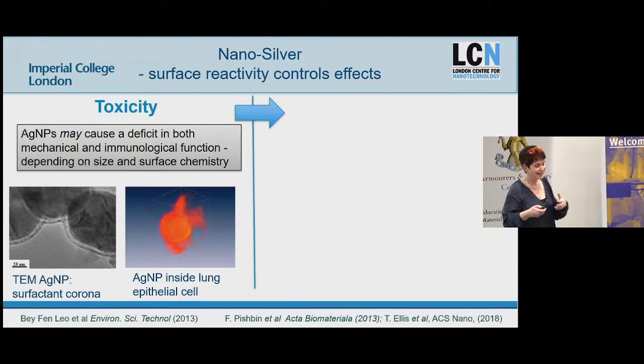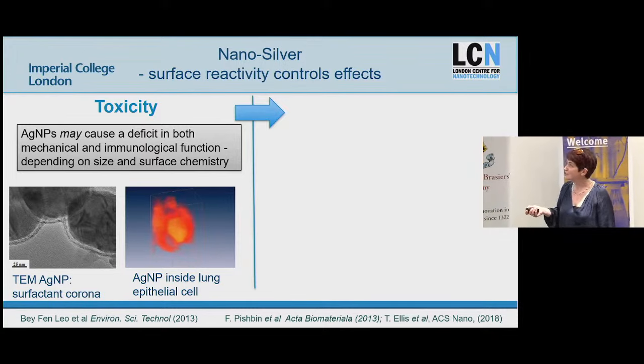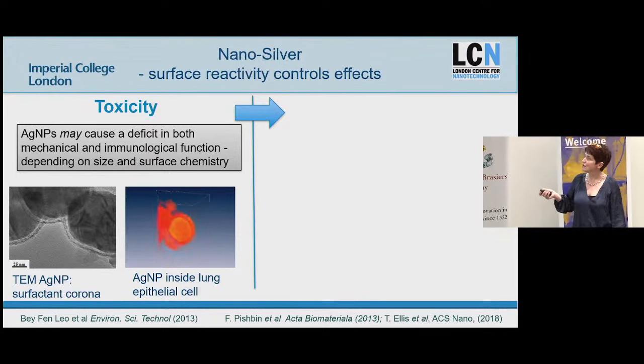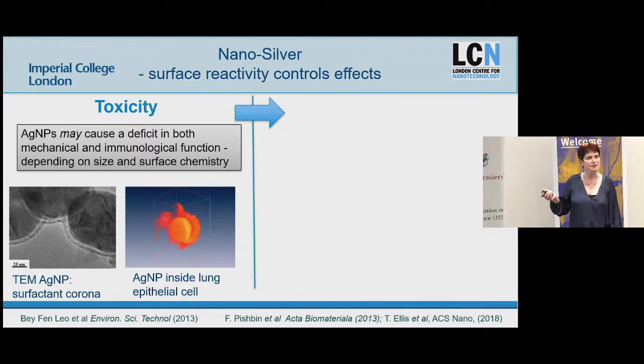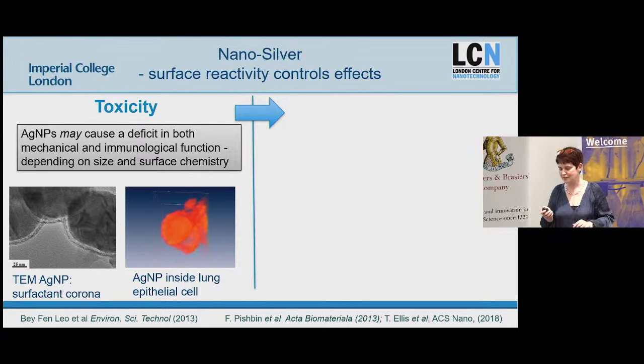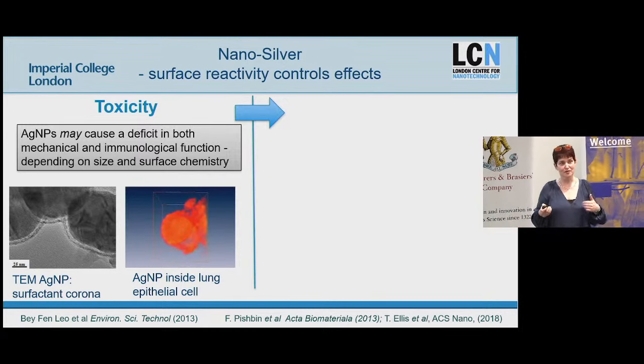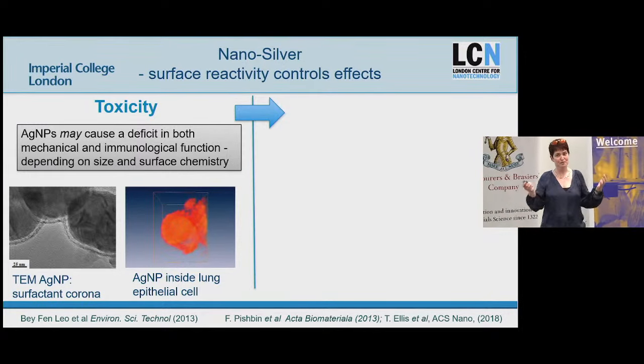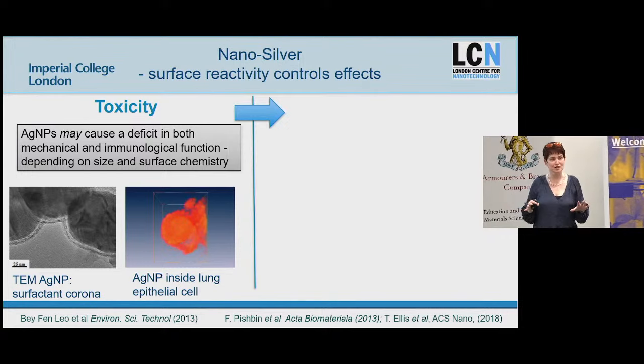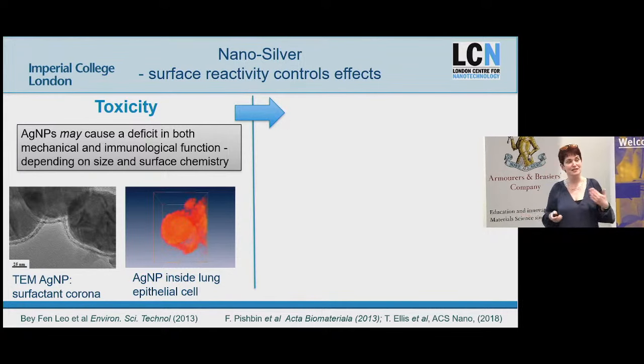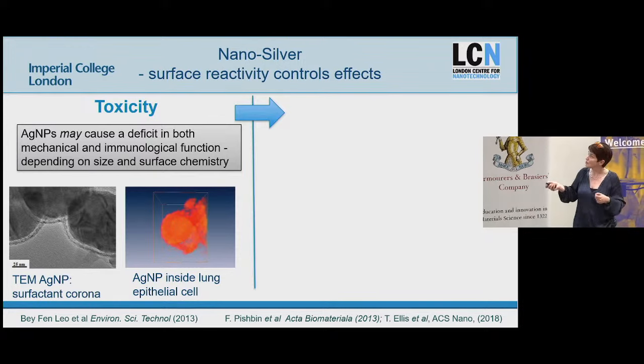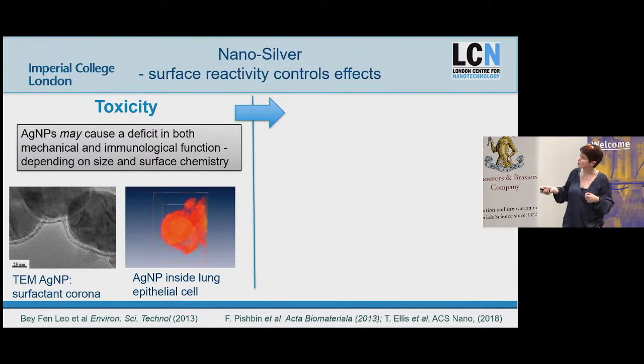Okay, it also dissolves a little bit, and in the lung there's quite a lot of sulfur, and silver loves sulfur. Anyone that's tried to polish jewelry or silver artifacts knows silver loves sulfur. So silver in the lung, when it tries to dissolve, meets sulfur and precipitates. You don't get any free silver ions for very long. It turns out that's a detoxification mechanism, this insolubility of silver sulfide. But you see it starts to dissolve, and then you get this cloud.